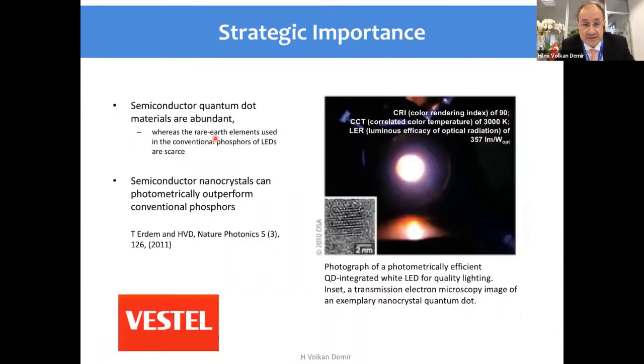So this hypothesis was correct, and this was one of our demonstrations where we were able to show that using this type of sharp emitters, one can have extremely high color rendering property. This means you can really reflect the true colors of an illuminated object. You can make it warm white, and you can make it spectrally very efficient. So these numbers at the time were highlighted in Nature Photonics. The difficulty was to reach these photometric metrics all at the same time. And this is indeed outperforming conventional phosphors.